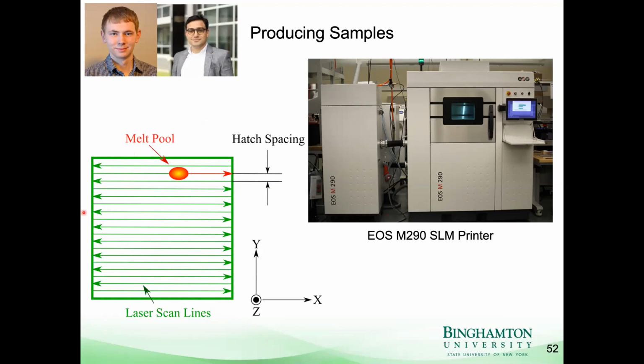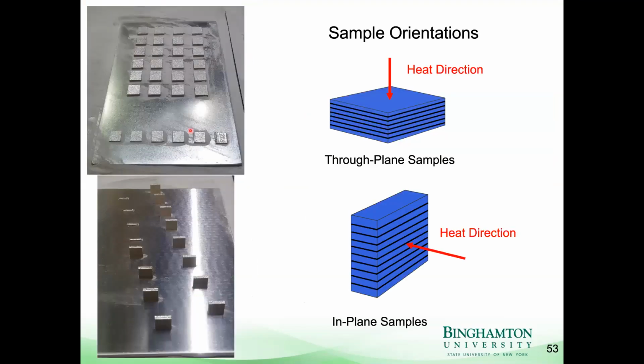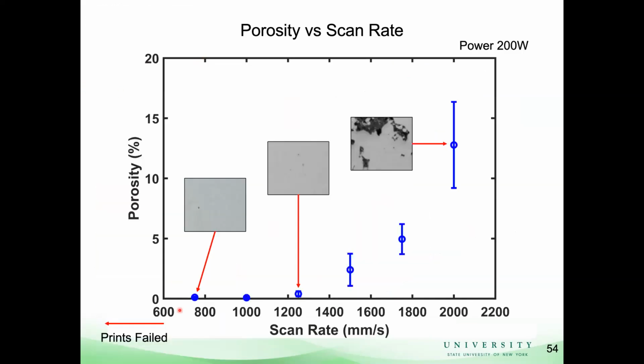And this stainless steel work was led by Jake Simmons. This was his master's thesis, and my PhD student Arad was also instrumental in this work. We printed samples in our metal printer in two different orientations: through plane test samples and in plane test samples. We want to measure how the thermal properties change with orientation as well as with process parameters. Each one of these squares was printed with a different laser scan rate, and we held the laser power fixed at 200 watts.